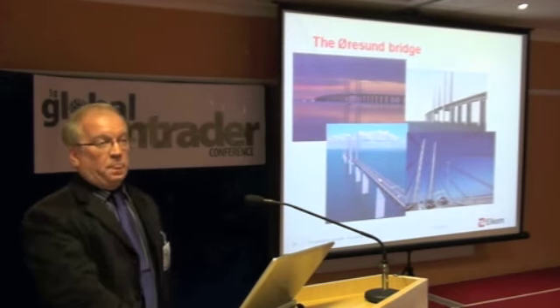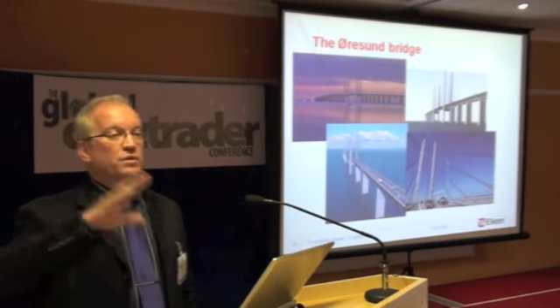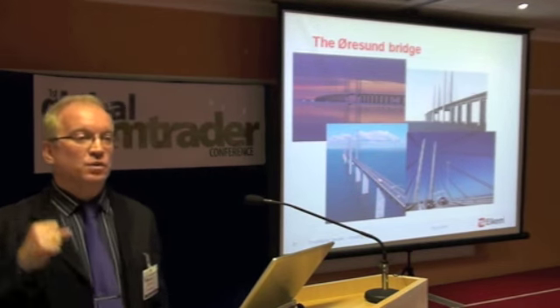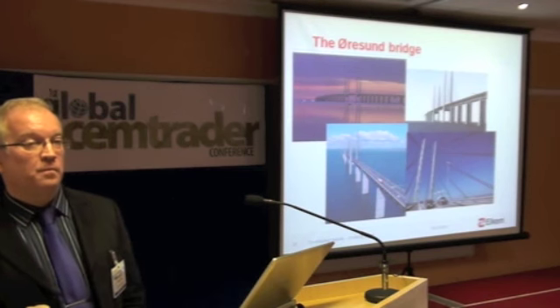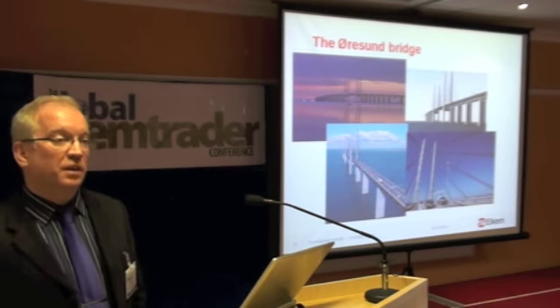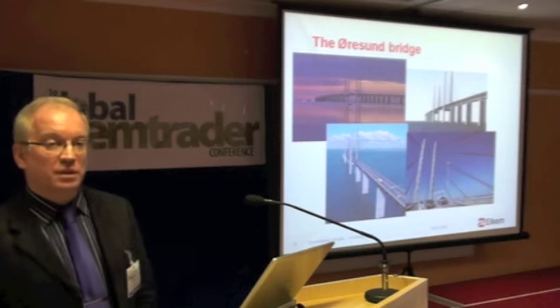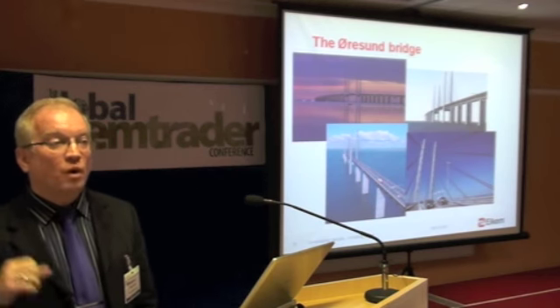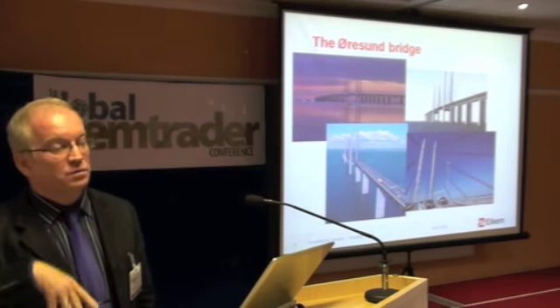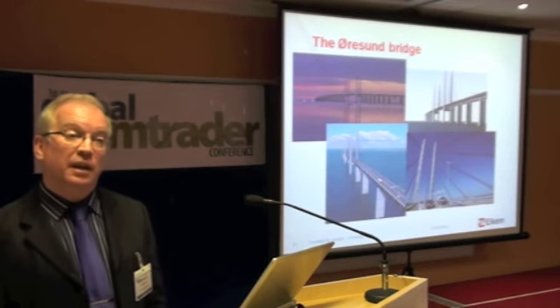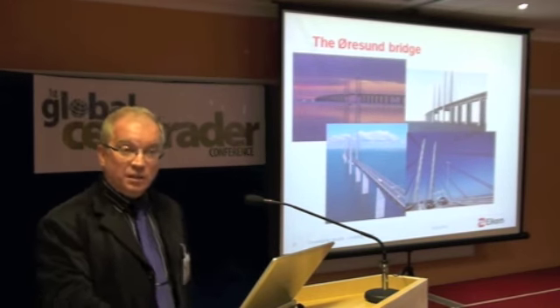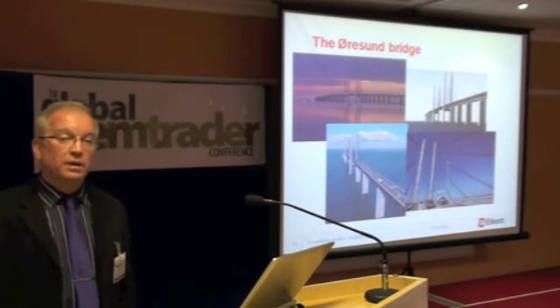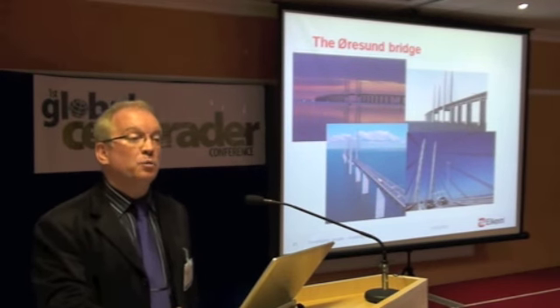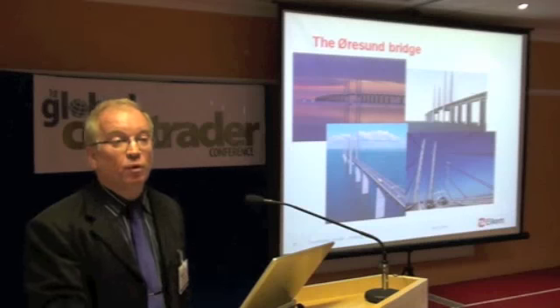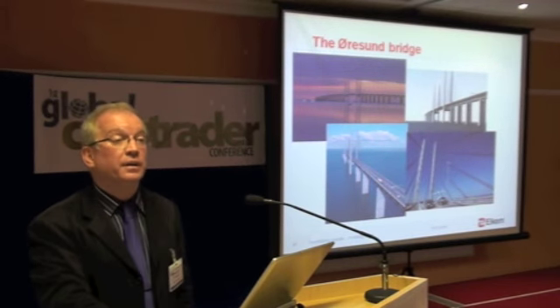Öresund Bridge, 2 different mixes, one from one side, one from the other. Swedish side was OPC and silica fume. Danish side was OPC, 15% fly ash, 5% silica fume. What they had, what they could use to get the performance in the concrete. Of course, the Danish side had already used it in the Storbelt. They'd used over 1 million cubic meters of ordinary Portland fly ash and silica fume blended concrete there.